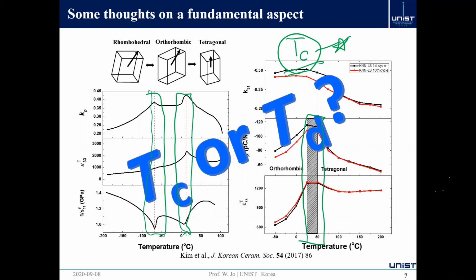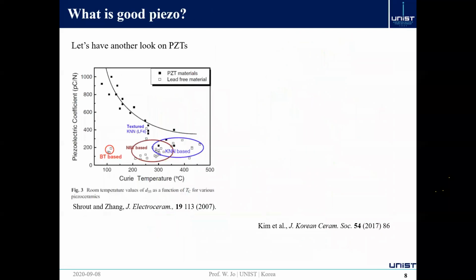I'm raising here is, when you develop a new material, do you have to consider TC or TD? I would say TD, the depolarization temperature, is more important. It could be a phase boundary, the polymorphism phase boundary could be TD. When it comes to single crystals, people usually say TRT, the rhombohedral to tetragonal phase boundary, or it could be the freezing temperature if you deal with relaxor materials. So the reason TD matters more than TC can be seen really straightforwardly from this example here.